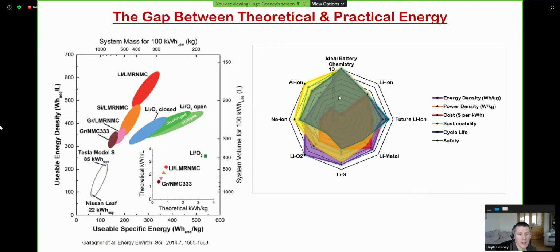And then finally, this is cycle life. So again, the ideal battery chemistry will be 10 out of 10. The future lithium-ion is likely to have a very long cycle life, whereas the higher energy density ones like lithium-sulfur and lithium-air will likely have a lower cycle life. But that's not necessarily an issue. If you can get, for example, 1,000 cycles at a very high energy density, you can actually get away with some of this.